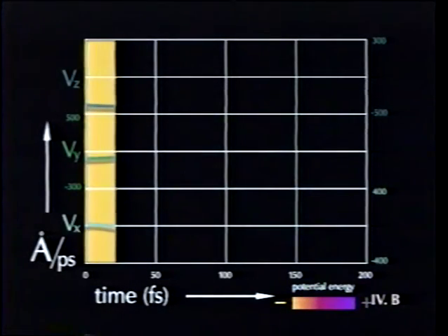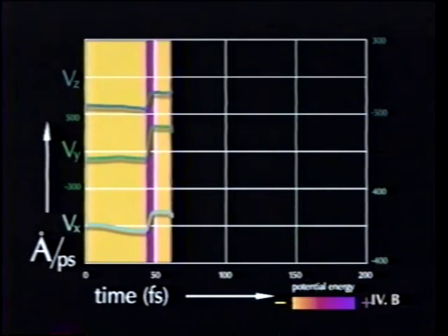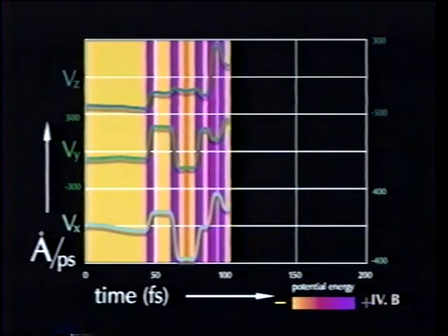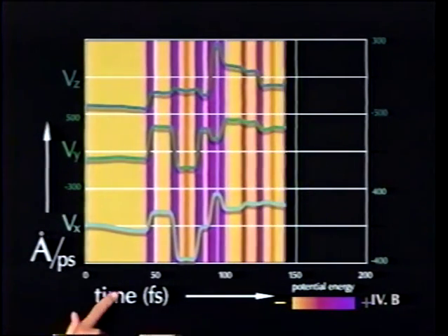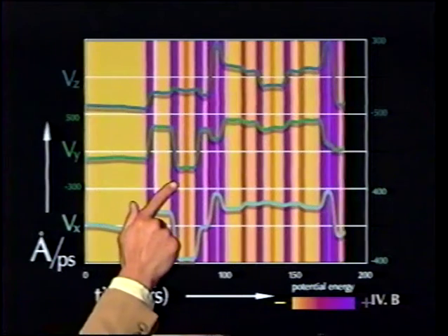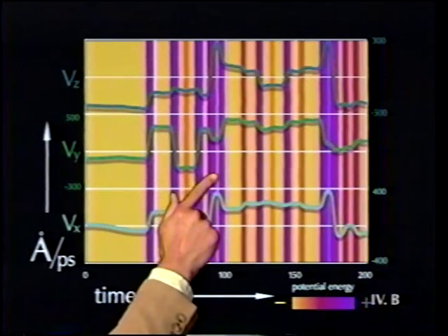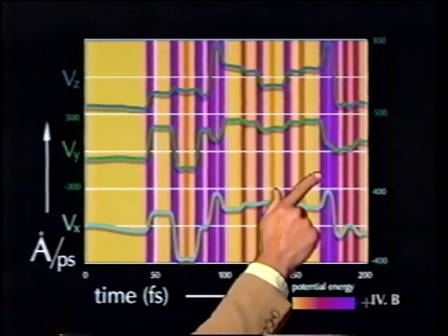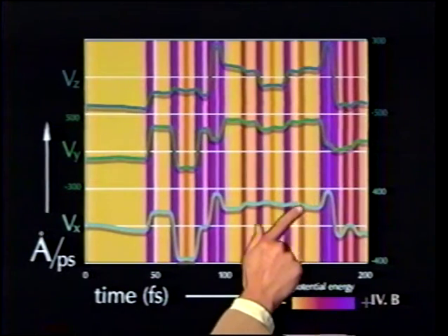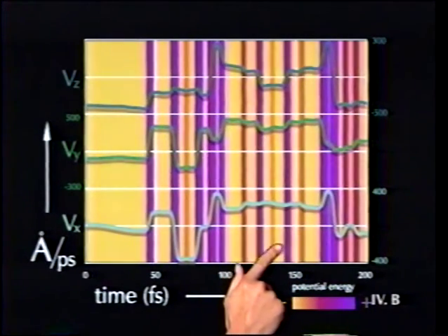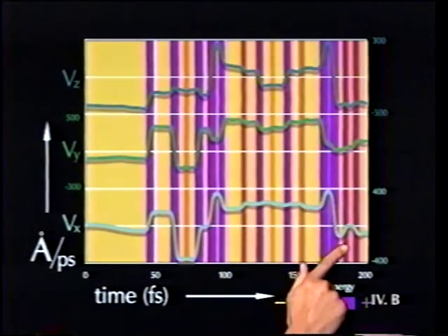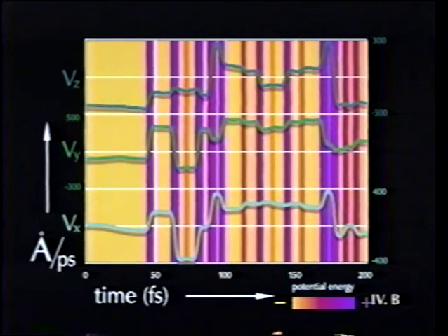The entire velocity plot shows the effect of the collisions and their magnitude. 7 hard binary collisions, purple, and 4 softer binary collisions, red, affect the path taken by the hydrogen. The energy of the hydrogen at the end of 200 femtoseconds is only 5% less than its initial energy.